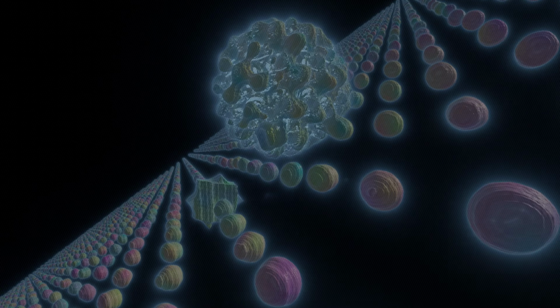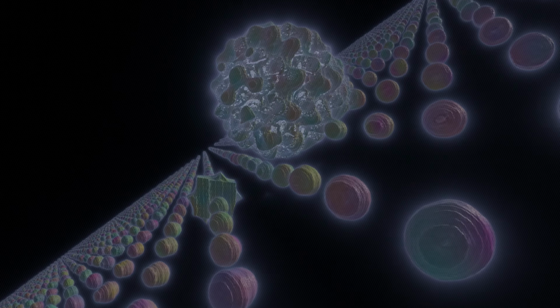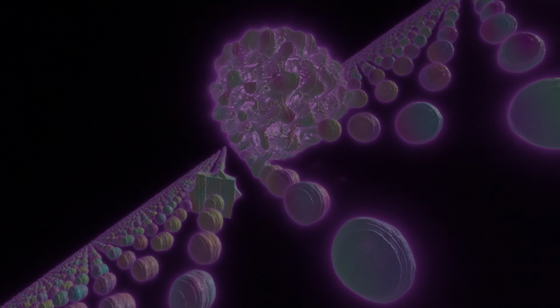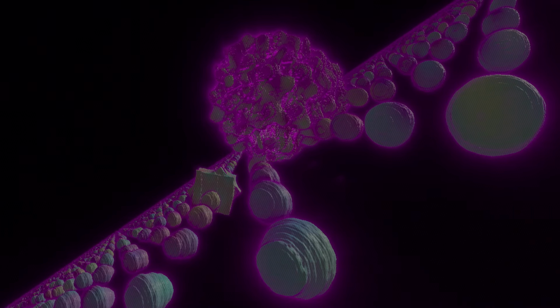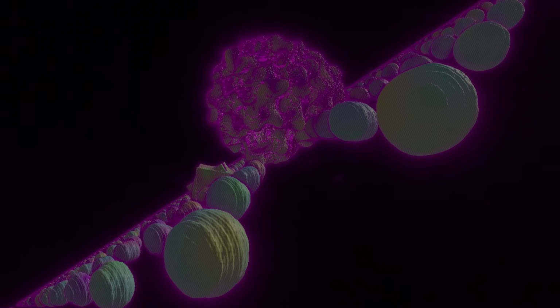Beyond phonons hitting each other, there's also the interaction between electrons and phonons. That sounds fundamental. Oh, it's hugely fundamental. The electron-phonon coupling is arguably one of the most important interactions in all of condensed matter physics. It governs so much. For instance, electrical resistivity in metals. Why does resistance go up with temperature? Because the vibrating lattice, the phonons, act as scattering centers for the conduction electrons. More heat means more vigorous vibrations, more phonons, more scattering events for the electrons trying to flow, higher resistance.